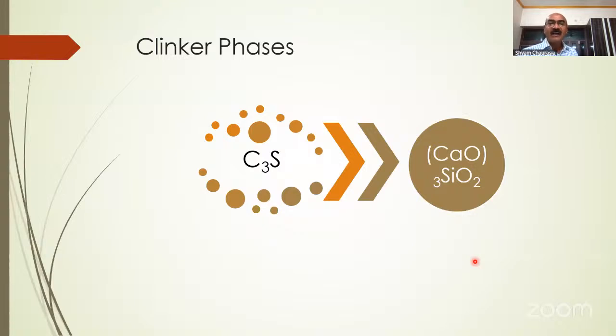As I have already shared, C3S is 3 parts of calcium oxide and 1 part of silica. These are the highest strength imparting components, responsible for giving the cement its strength. Otherwise, if you crush limestone, it won't give you any strength. Before calcining it, before it becomes CaO and other forms, the limestone itself won't give you any strength. So it has to convert into C3S, C2S.